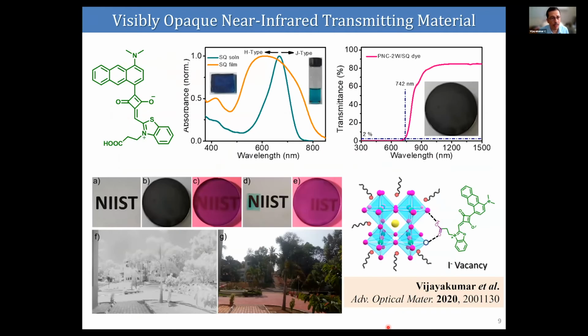And we have also developed visibly opaque and near infrared transmitting material. These are useful for night photography applications as well as for security applications. We have incorporated squaraine dyes with this material by generating iodide ion vacancies in this material, and by incorporating the squaraine dye molecules into this perovskite matrix, we were able to get an opaqueness up to 742 nanometers. That means this material can completely absorb the entire visible spectrum, but at the same time, we can get nearly 90% transmittance in the NIR region. So this is very much suitable as a visibly opaque, near infrared transmitting material. Again, we published this last year in Advanced Optical Materials.